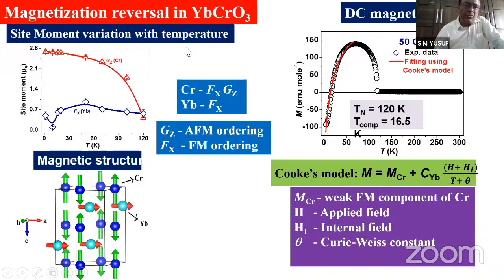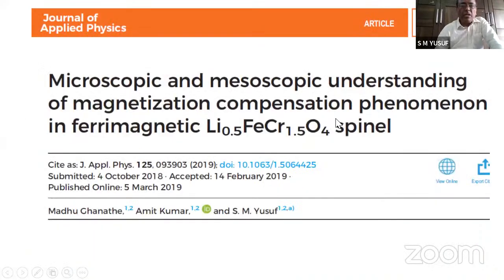I will not go into details here. This is a magnetic structure to explain the microscopic origin of magnetization reversal. The DC magnetization we have also modeled using the Cooke's model, where we have taken the ferromagnetic moment from chromium, because there is a little canting of the chromium moment, not perfectly antiferro, and the ytterbium moment, and by taking the external field and internal field, we are able to reproduce this magnetization reversal. This is another example from the spinel systems, where, by the way, there is other interest with regard to lithium battery materials. I will not go into that.